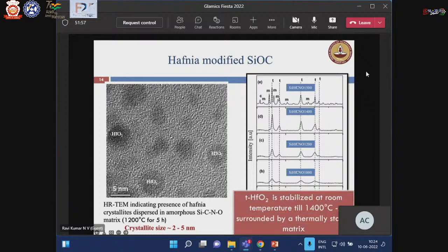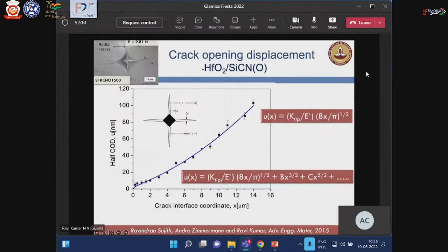As we demonstrate here, tetragonal hafnia is stabilized at room temperature till around 1400 degrees Celsius without transformation, but even at 1500 degrees Celsius we see partial transformation to a monoclinic phase. We have done some fracture toughness study to find out the fracture toughness in such bulk semi-crystalline or partially crystalline materials using crack opening displacements, and typically they are in the order of around 1 MPa root meter, not very high. So we never use these materials directly for structural applications; typically they are used as matrices for CMCs so that we can use them for structural applications.